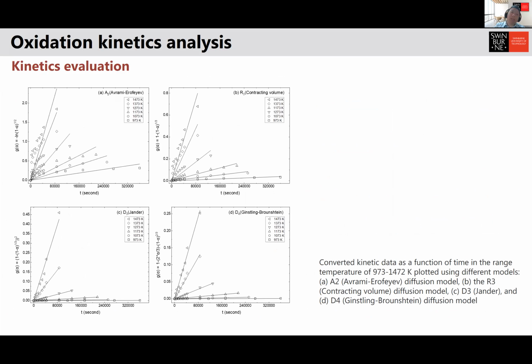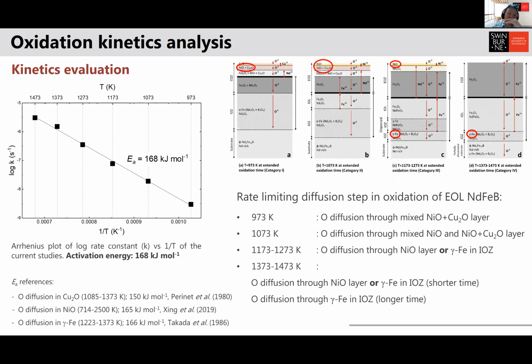And we found that the activation energy is about 168 kilojoule per mole. And this one is actually similar to the activation energy for oxygen diffusion in copper oxide, oxygen diffusion in nickel oxide, and oxygen diffusion in gamma Fe, right? Roughly in that sort of region. So considering the microstructure form, we sort of deduce that the rate limiting step in this oxidation is in a sense diffusion, right?